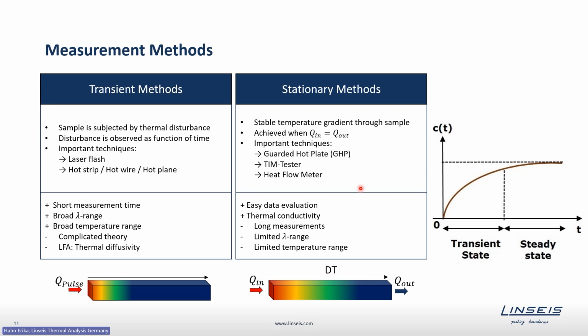On the other side, we have also the stationary methods. Here, one needs to wait until there's a stable temperature gradient through the sample, and we have a stable heat flux going in as well as out of the sample. And to these methods belong, for example, the guarded hot plate, the TIM tester, or the heat flow meter methods. A disadvantage here is that as we have to wait for a stable state, measurements take quite long. And additionally, also the thermal conductivity range is quite limited, as well as the temperature range. Mostly these methods go up to maybe 100 or 500 degrees Celsius. But an advantage is that this investigation delivers directly the thermal conductivity.